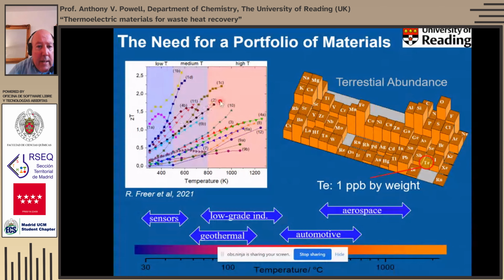Whereas something like lead telluride, which is this one, for instance, shows its higher performance at much higher temperatures, in this high T region. And similarly, we have other materials, for instance, boron carbide here, which is the one in black, number 12, that keeps on going up and will just keep on going up for quite some way beyond 1200 Kelvin. So it's a high temperature material. So we really need to be able to design materials towards the temperature appropriate to specific applications.